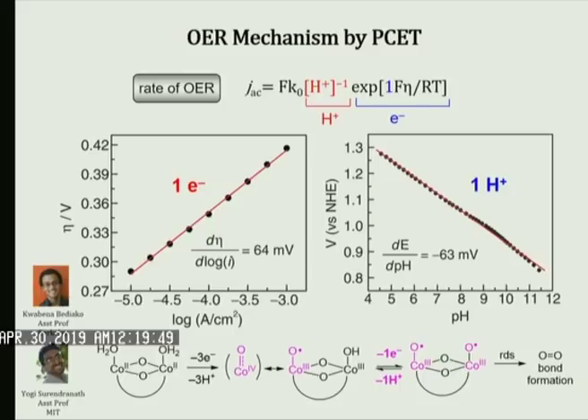So from these things called Tafel plots, if you do electrochemistry, you can look at things like the voltage as a function of how fast I'm making oxygen. That's on the y-axis. And I can look to see how fast do I make oxygen and at what voltage do I make oxygen as a function of pH. We get this rate law for oxygen production.